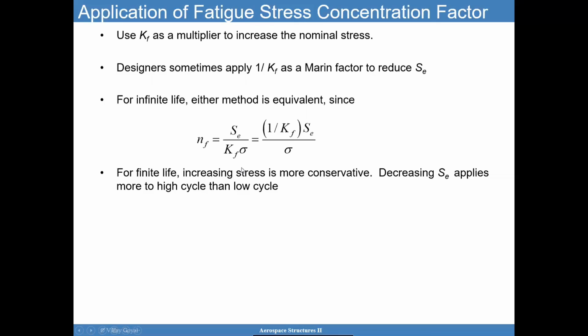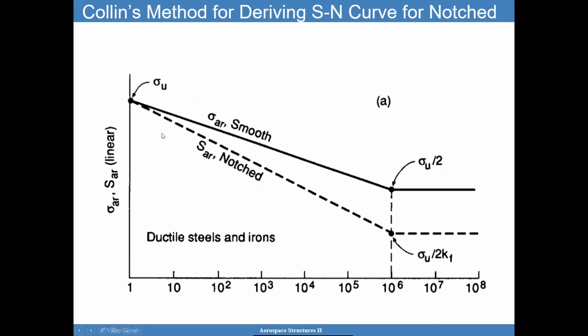But it is important to consider, and this is the Collins method to derive this fatigue life curve. You basically want to knock it down by sigma ultimate divided by twice Kf. Here, this is the endurance limit for steel, so that's why it's sigma ultimate divided by 2, and then you further knock it down by Kf.